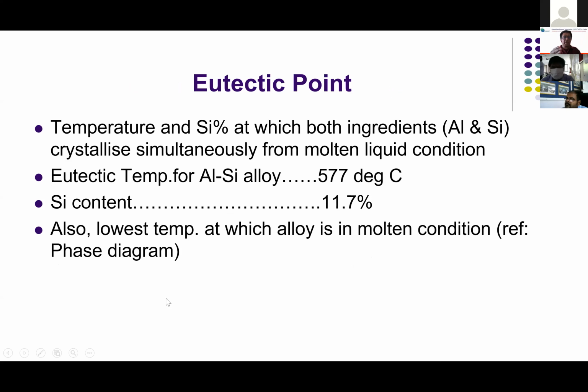Now, we are talking about the eutectic point. Here I mentioned 11.7. Many papers indicate that the eutectic silicon content is about 12. So we normally go by this 11.7%. Eutectic temperature is 577 degrees centigrade. Also the lowest point at which the alloy is in the molten condition.